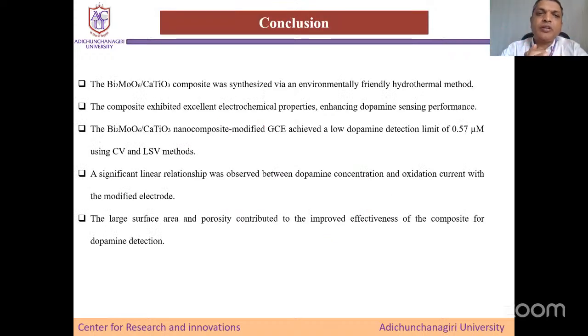So in conclusion, we were able to synthesize and fabricate both the nanocomposites, which can be used for energy harvesting and then sensing. We have also synthesized metal oxide nanocomposites for the detection of drugs as well as dopamine. A significant linear relationship was observed between dopamine concentration and current, particularly in the second one, where, detecting dopamine using bismuth molybdenum oxides, we were able to detect dopamine even at micromolar concentration. That is largely because of the large surface area and porosity of the nanocomposites.